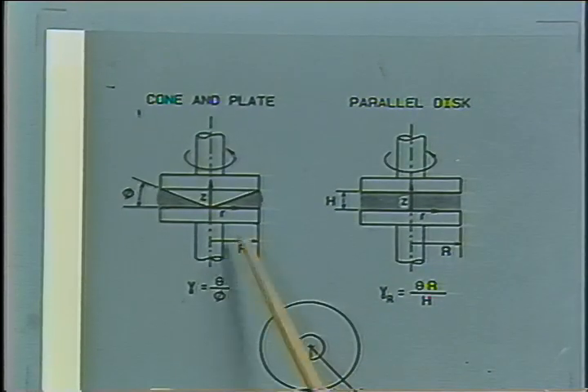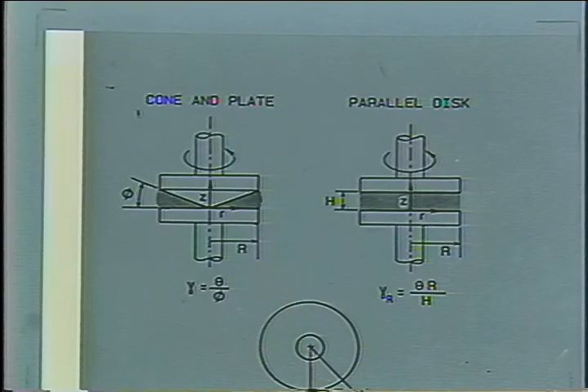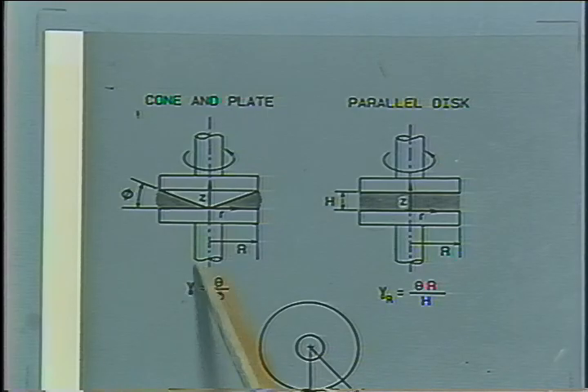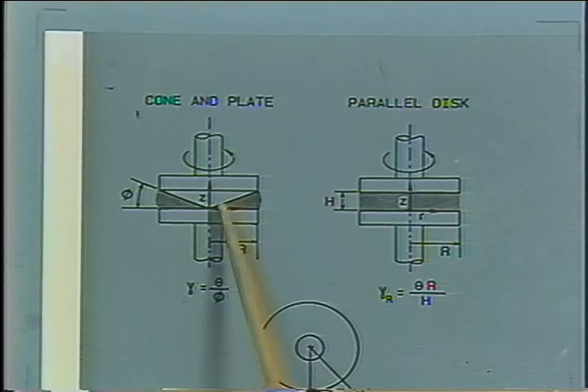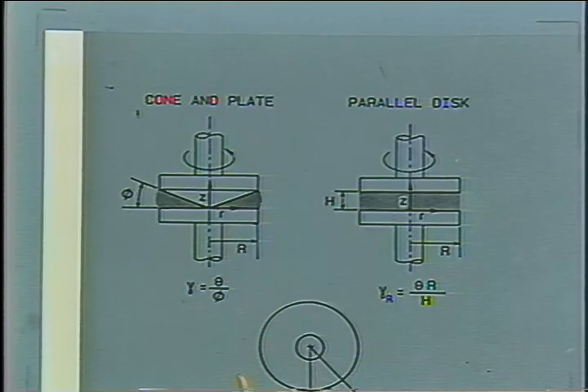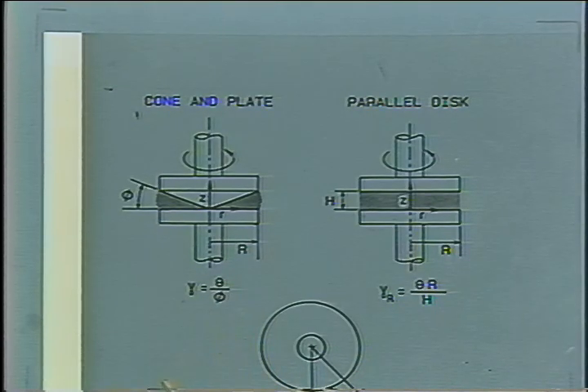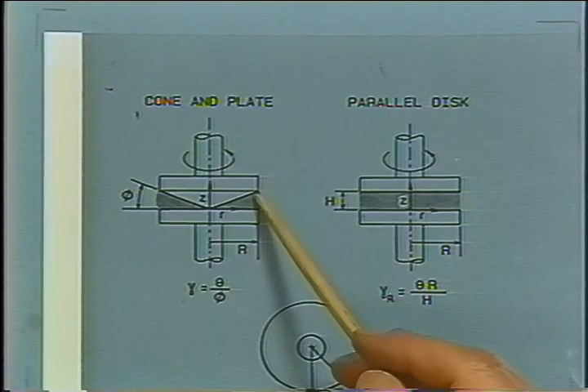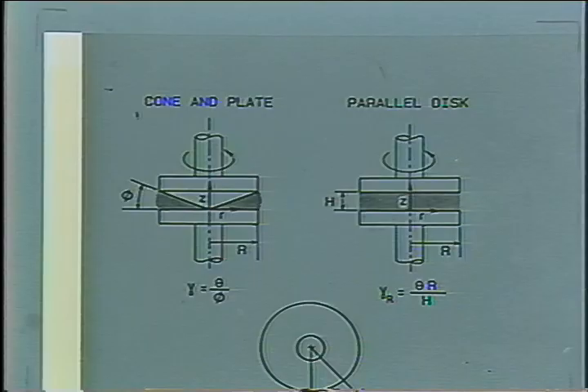Now, we could do that experiment in a cone and plate geometry where the strain is homogeneous and everything is easy to analyze, everything is fine. There's one experimental problem which we encountered here. When you want to have a large deformation, say maybe 25 or 50 shear units, a very large strain in that system, then the cone has to rotate quite a bit to obtain that strain. And that will change the surface and will cause problems in your system.